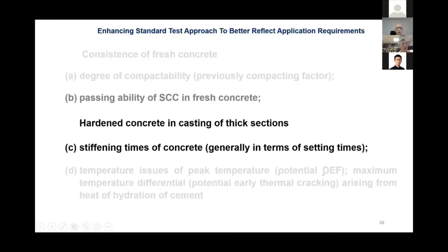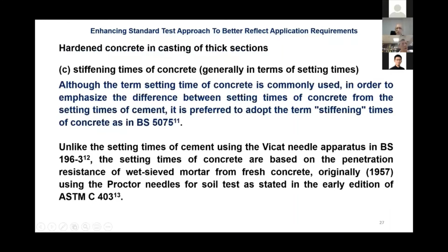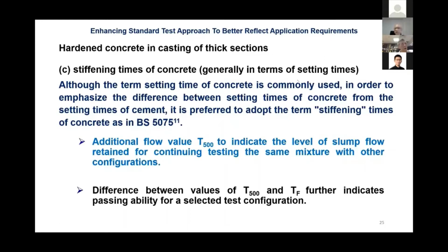This is what we call the stiffening time of concrete. Now, of course, in practice, they call it the setting time. I do not like the term setting time because we have setting time of cement, from which we make the same concrete. And yet the setting time of cement and the setting time of concrete using the cement are completely different test methods, with different values, and they do not even have a direct linkage other than that if one is better, the other will be better. So basically, I would like to call it stiffening time because our concrete is stiffening, not setting.